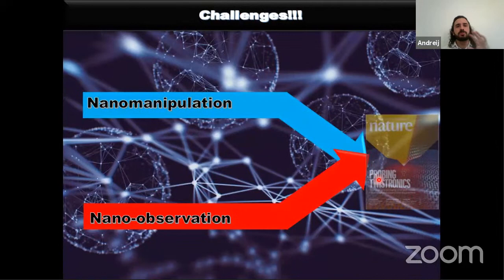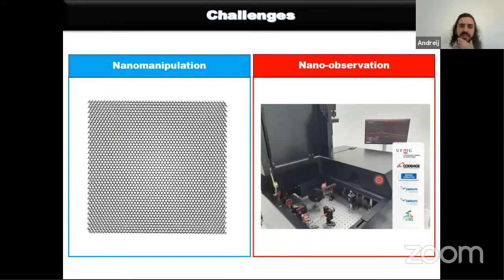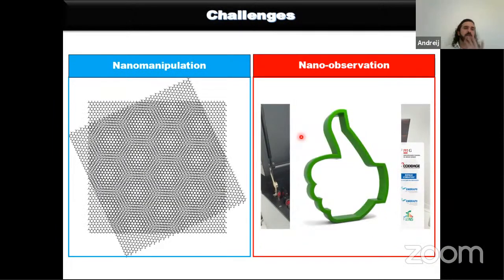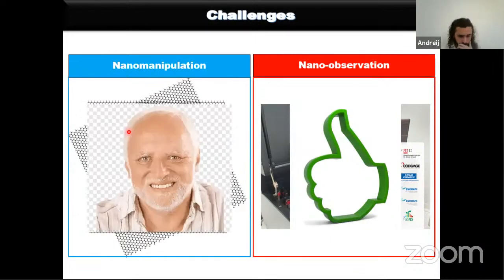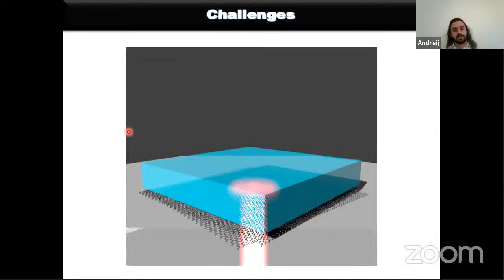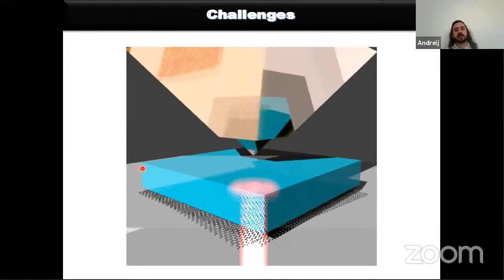Okay, so I will go now to some challenges that we find by trying to cross the nano manipulation and nano observation paths. In the case of nano observation, we have commercial equipment, which is well established, so it's okay. But on the nano manipulation side, it's a little bit tough because it is really hard to precisely rotate one layer of graphene on top of the other. Okay, so this is not so easy, and we have another challenge, which is that when people nowadays prepare these TBG samples, they use a very thick boron nitride flake on top of it, which prevents our nano antenna from interacting with graphene. So we need to get rid of this bulk